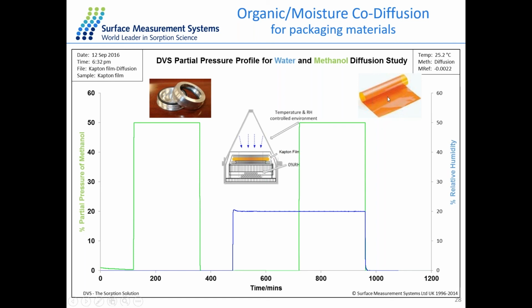Here we use Kapton film sample as an example. And we measure the water as well as the methanol diffusion on this film sample at different temperatures. And this methanol just represents a kind of flavor molecule used in the food industry. So it can be any kind of organic vapors. And we designed this method basically in 3 different parts. The first stage is the methanol only stage, with 50% methanol vapor flowing through the film. And then the second stage is the water only stage, so 20% water.